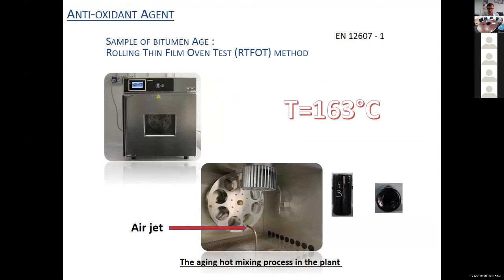In order to study the effect of aging in the laboratory, the method known as the rolling thin film oven test was adopted to simulate the short-term aging of asphalt binder that would occur during the hot mixing process. The apparatus consists essentially of an internal double-wall furnace in which the hot air circulates, conveyed by an internal fan, at the test temperature of 163 degrees. The test consists in subjecting a thin layer of bitumen to a hot air jet for 75 minutes.